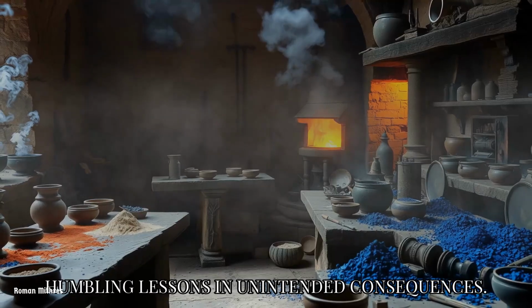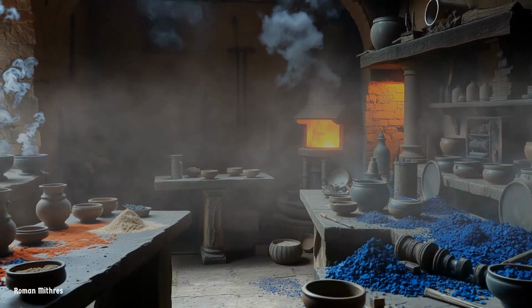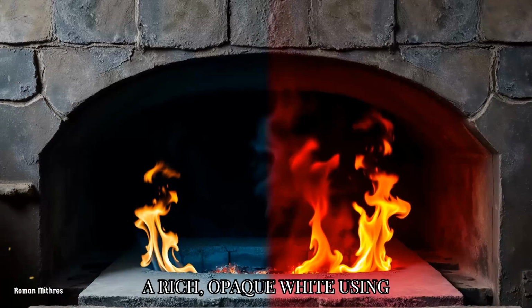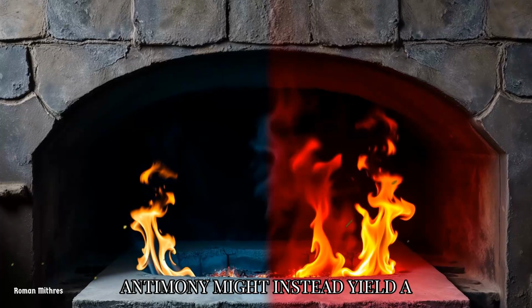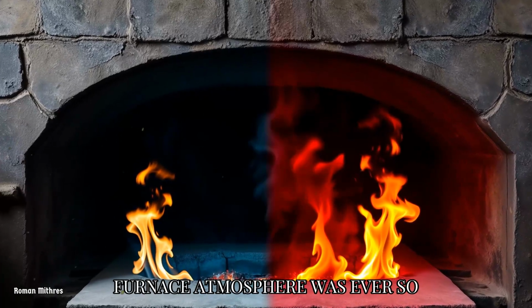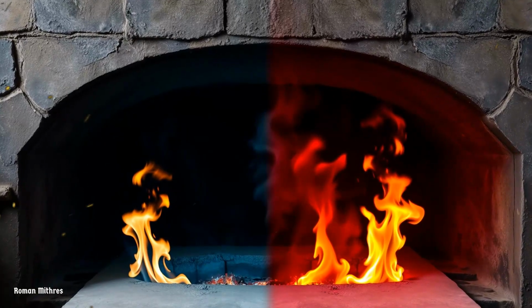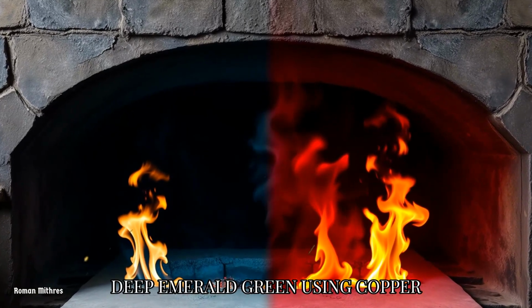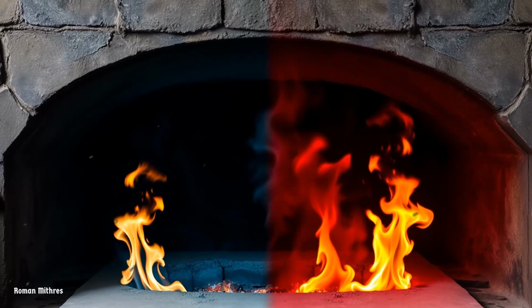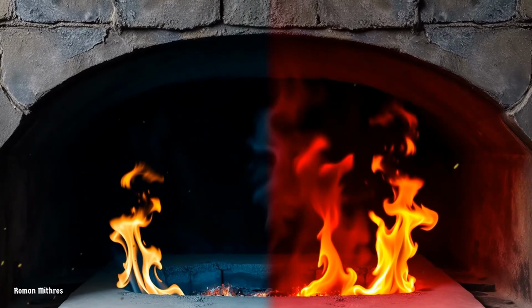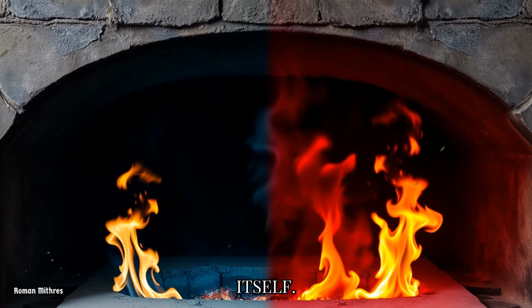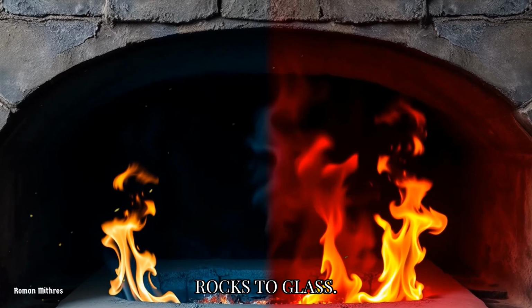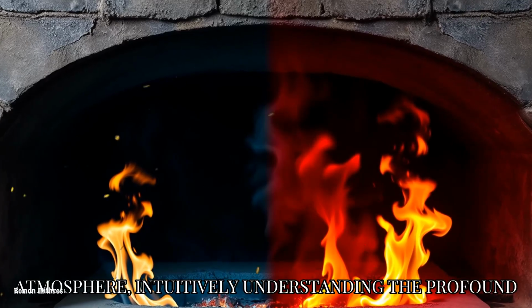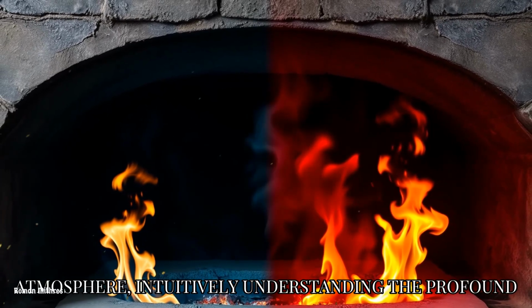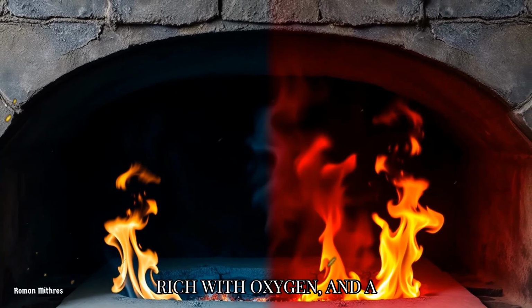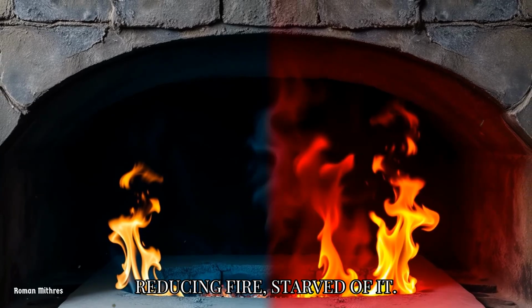The first attempts are often humbling lessons in unintended consequences. A batch intended to produce a rich, opaque white using antimony might instead yield a sickly, pale yellow because the furnace atmosphere was ever so slightly off. A mix designed for a deep emerald green using copper might emerge as a disappointing, pale turquoise for the same reason. This is where the Romans' true genius begins to reveal itself. They weren't just adding pretty rocks to glass. They were masters of furnace atmosphere, intuitively understanding the profound difference between an oxidizing fire, rich with oxygen, and a reducing fire, starved of it.